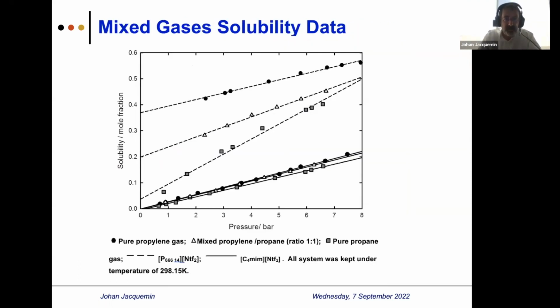recently, I would say. Anyway, just to give you an example using such a technique, we determine, and please look only at the first line, the propylene and propane solubility in this ionic liquid P6614 NTF2. And this is a single gas solubility. There are two lines: the circle is the pure propylene solubility, and the gray square is the pure propane solubility.